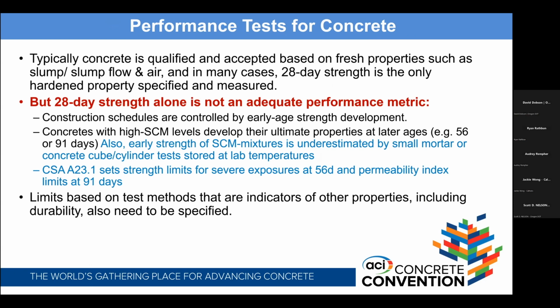Now, typically, in most specifications, concrete's accepted based on the fresh property slump or slump flow and air. And in many cases, the only hardened property specified is the 28-day strength. But that's not an adequate metric for performance. Often construction schedules are controlled by early age strength, which then puts requirements on perhaps cement content and water cement ratio to get those early age strengths, because people talk about 28 days, but they often want 1 day strengths or 3 day, especially in vertical construction.